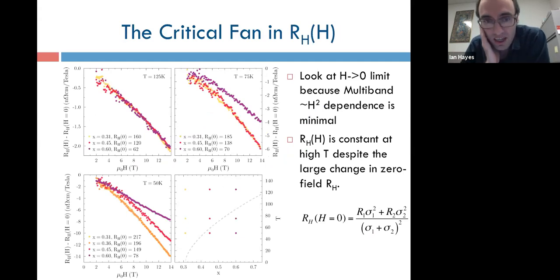Now, the second thing I'd like to show you in detail in the data is what the fan looks like at higher temperatures. So if you go to very high temperatures, what I've plotted here is RH minus RH of 0. So this is just the field-dependent part of RH, which I do to compare samples from different parts of the phase diagram that have fairly different background RHs.